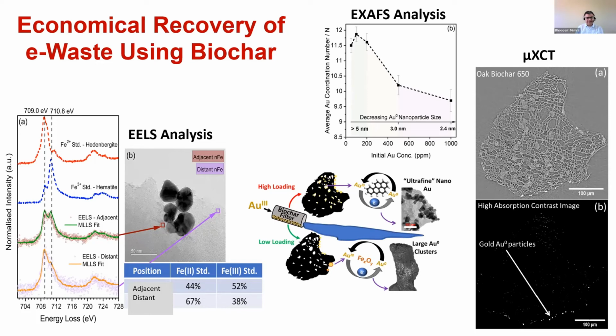How can we rationalize that? Initially, it turns out that these mixed iron 2,3 oxides are the active sites, and they form rather large gold clusters on the surfaces. As the loading of gold increases on this biochar, these relatively less potent reductants, like quinones or reduced sulfur groups, reduce gold more in a monatomic form, and that is embedded in the mesh of the biochar carbon. Hence, we came up with a threshold, in terms of milligram per gram of gold to biochar, which will be very economically useful and very economic in terms of recovery of gold from wastewater.